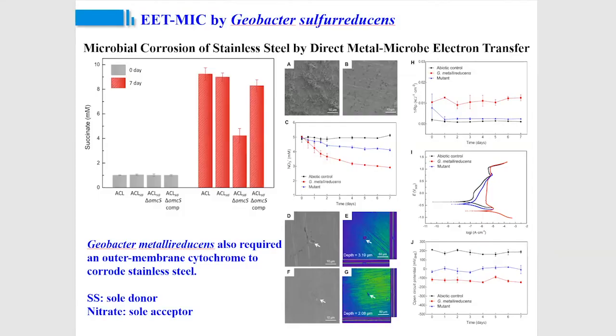Yes. Dake, if you go to one of your polarization plots, I'm intrigued that when you have microbial activity, your potential and current show high corrosion rate or susceptibility. But after some point, when you increase the potential, it stabilizes, like it is a passivation type of phenomenon in the microbial environment. And it was there in other polarization plots as well. Why is that? This is a very good question. I think you can see that even though we have biofilm, the coverage for the biofilm is